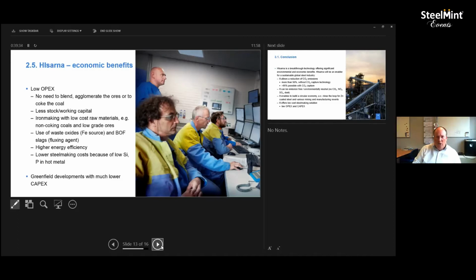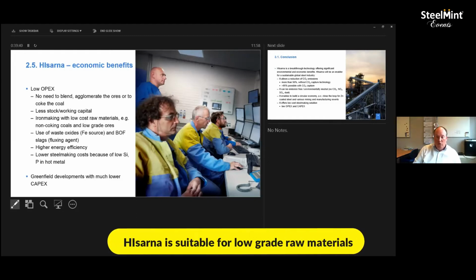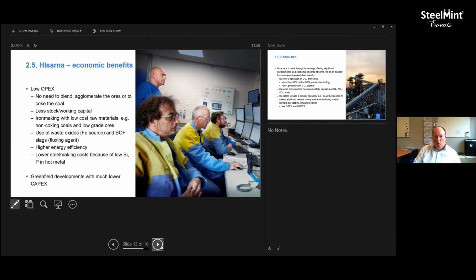HIsarna is actually quite suitable for lower grade raw materials. We don't need any coking coals, so that will save us quite a bit of money, I guess. And also in the type of ores we use, we can be a lot more flexible than on the blast furnace. And one of the key advantages for us is that we separately tap the slag and the metal. So if we have a grade of ore that produces a bit more slag, it's not necessarily hampering the process as such.